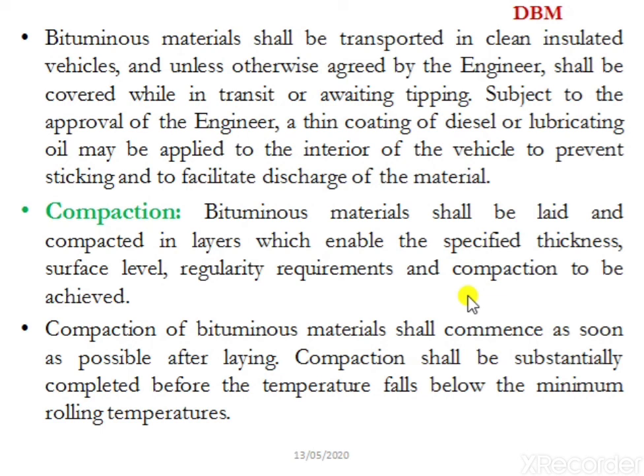During this rolling, wheels of the roller shall be kept moist by sprinkling water from the water storage fitted with the roller, to prevent the mix from adhering to the wheels. The roller shall proceed on fresh material with the rear or fixed wheel leading, so as to minimize the pushing of the mix. In the portion in camber, rolling should begin at the edge, with the roller moving forward and backward until the edges have been firmly compacted. The roller shall then progress gradually towards the center, parallel to the center line, uniformly overlapping each of the preceding tracks by one-third width until the entire surface has been rolled.